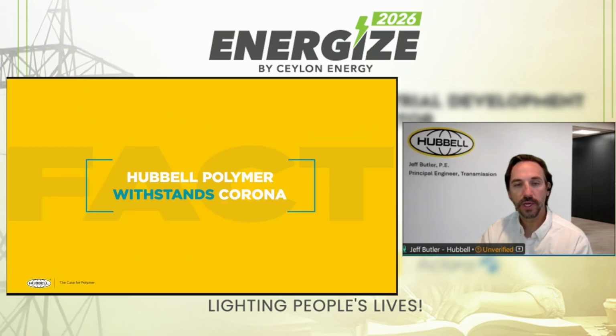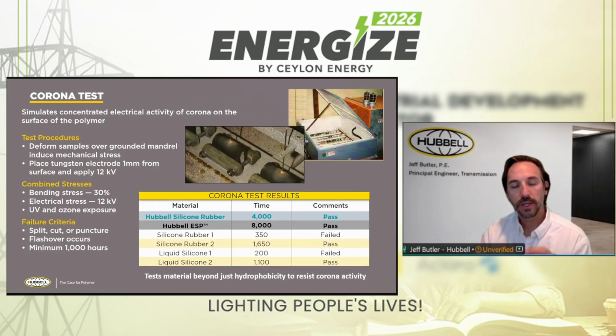The other was we were looking at corona. I referred to this corona phenomenon. So we took an electrode, placed it 1 millimeter from the surface of the rubber, and energized it at 12 kV. You're basically forcing corona and high electrical stress right on the surface of the rubber. In the multi-stress test, there was moisture and humidity, and so the silicone rubber, with its hydrophobicity that I had discussed previously, performed superior to the ESP.